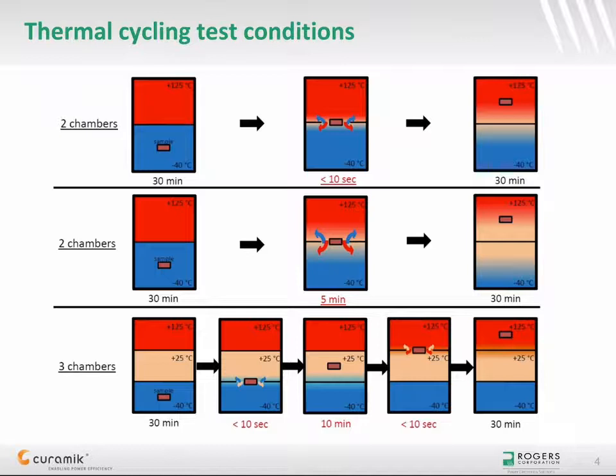First, the transition time between cold and hot chambers can be very short in the case of thermal shocks, usually less than 10 seconds, or much longer, up to 5 minutes. In some cases, manufacturers may perform this test with 3 chambers to provide an intermediate plateau at room temperature. Second, the duration in cold and hot chambers may vary between few minutes up to many hours, but 15 to 30 minutes are typical values.